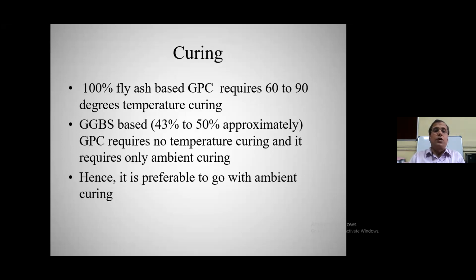For curing, 100% fly ash based GPC requires 60 to 90 degrees temperature curing, but GGBS based concrete requires approximately 43 to 50. The percentage of GGBS which is required is 43% to 50%, and beyond that, the strength decreases. This is what we have observed in our investigations. Hence, it is preferable to go with ambient curing with the above GGBS 43 to 50% in fly ash.